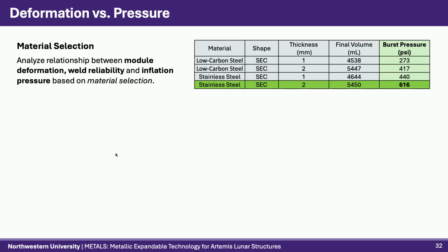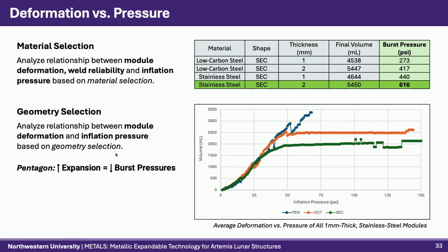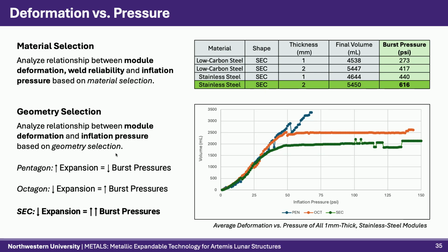Material selection was found to only influence burst pressure. While both low carbon steel and stainless steel 304 produced similar final volumes, stainless steel 304 demonstrated a maximum burst pressure of 616 psi, highlighting its superior longevity and pressure tolerance. Regarding geometry, pentagons achieved the highest deformation but the lowest burst pressures of around 70 psi. In contrast, octagons and SECs achieved similar deformation, but while the former burst at 140 psi, the SEC, as mentioned previously, survived pressures up to 600 psi.